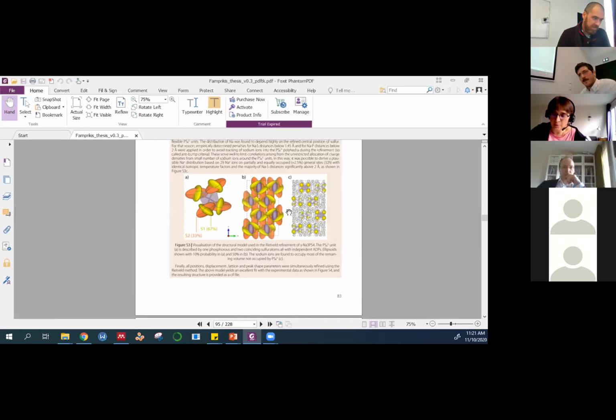Maybe I'll move to another question slowly. This structure solution, you explained nicely that you found it by analogy with Na2SO4. I was wondering then, why didn't you try to reconstruct it from the alpha and beta polymorph? Because you nicely show the relation in chapter 6 between the alpha and beta polymorph, with the sodium slightly moved and the PS4 slightly tilted. But actually, this is obvious when we see tetragonal and cubic. So obviously there is a group-subgroup relation, and even when you look at the patterns, it's completely obvious. Here, can you find some crystallographic links between the gamma phase and the beta phase?